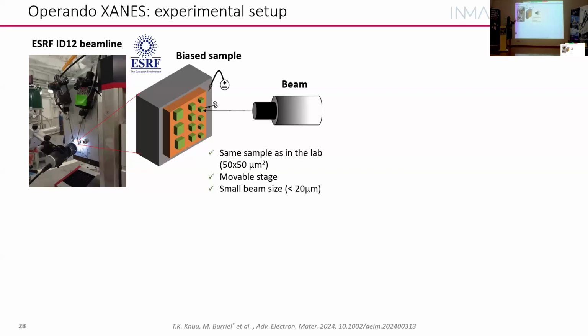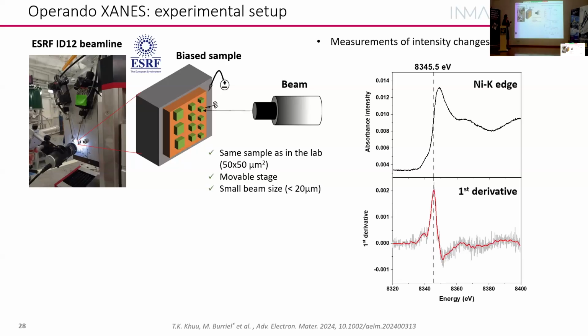So here, this is at the ESRF synchrotron at ID12 beamline. So we did the experiments as in our lab in the same conditions, because we just placed the sample here with the electrodes. We were biasing in the same way and measuring at the same time. So if you have done these type of measurements, you know probably that it takes quite a long time to have a good spectra for example, your nickel or whatever edge.